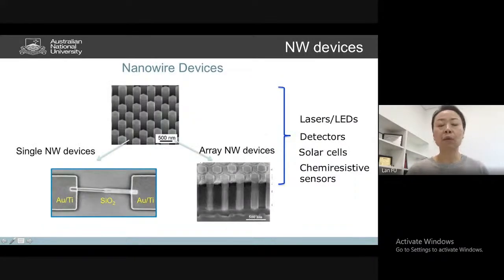So here's an example. Once you have nanowires grown, because they are so tiny, you need to imagine those images taken under an electron microscope. It's not a normal optical microscope, because they are nanometer size. You can see this 500 nanometer scale bar. This is an image taken under the scanning electron microscope, where you can really see nanometer sizes, down to about 1 or 2 nanometers. That's why we can see them. But if I have a sample to show you, with thousands of nanowires on the substrate, you won't be able to see it very clearly, because they're just so tiny.